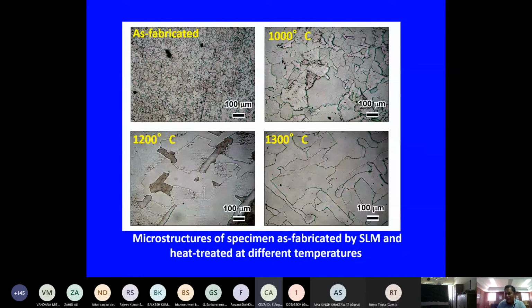So basically, this is a metallurgical aspect, because when we are doing the heat treatment, the mechanical property of titanium or titanium alloys may go down. You can see the as-fabricated samples have very fine grains, but when you heat above 1000 degrees, the grain size increases, and that may affect the mechanical property of my 3D printed component. That's why we do a lot of mechanical and engineering studies to find out whether the strength I am able to develop is sufficiently high, or compatible with the existing bone, so that the implant fixation holds and the implant can stay in the body.